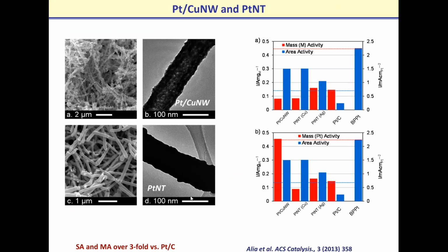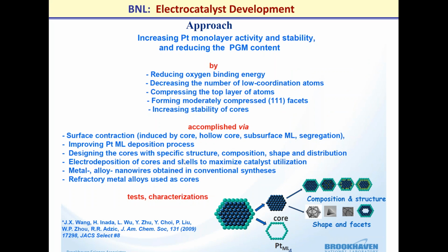It's also important to mention several other studies. This is Yushan Yan from Delaware, in collaboration with Brian Pivovar from NREL. So, platinum copper nanowires, in fact, where they can control the alloying to the extent where the system becomes stable. Also very well known from Brookhaven lab is the so-called platinum monolayer approach, where they carefully coat by galvanic displacement. They coat the so-called platinum monolayer, but that shouldn't be confused with a single atomic layer. This is just a platinum shell type of coating on different kinds of materials. And I would say the most famous example is palladium coated with a platinum shell.